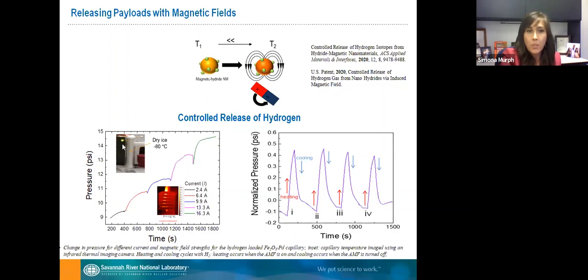So what we did here, we put our nanoparticles in the vial, and while kept in dry ice, we placed them in the magnetic field. And just by increasing the magnetic field, we were able to release the hydrogen, which was measured through the pressure in the headspace. When it's really cold, the hydrogen gets absorbed into the palladium. Once you heat it, it comes off, and you can actually measure the pressure. You can see here on the right the heating and cooling, and you can really monitor this process, and it is a really efficient process. I would like to mention that yes, we have another patent on this, and we also published in a couple of journals.